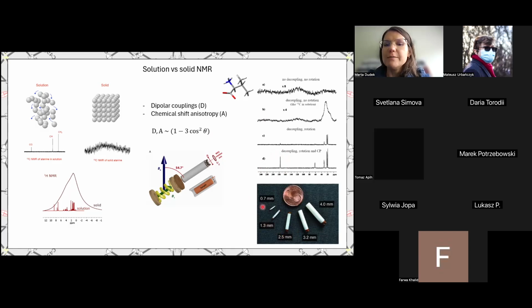This is not the most up-to-date picture. It shows different solid-state NMR rotors, so the containers in which we put a solid-state sample to measure it. The smaller the diameter of a rotor, the faster we may spin. We are mostly using in our applications 1.3 millimeter rotors, and in that kind of rotors you can usually spin with the spinning speed of 65-70 kilohertz.